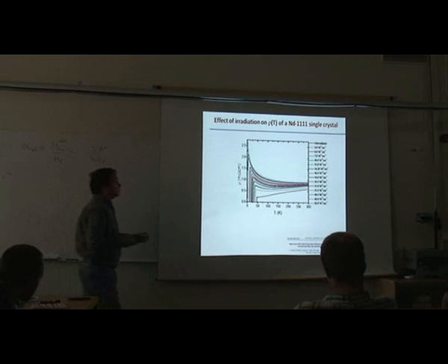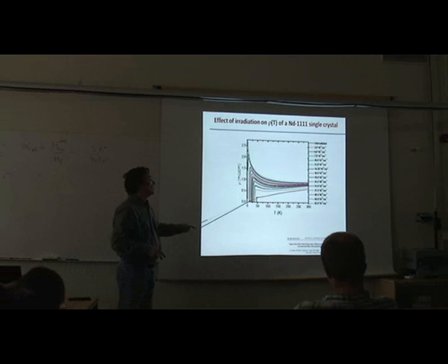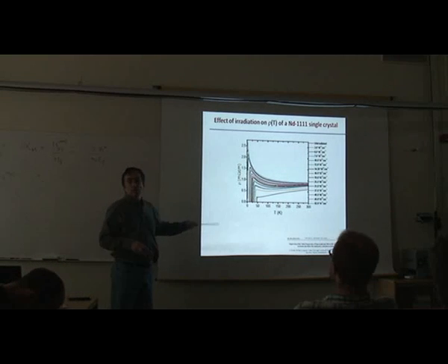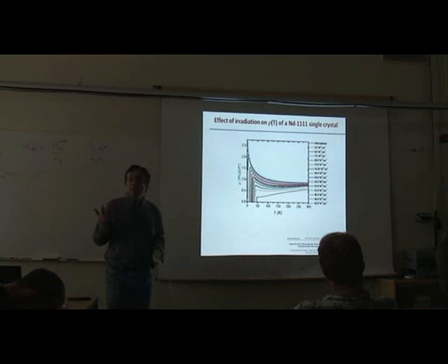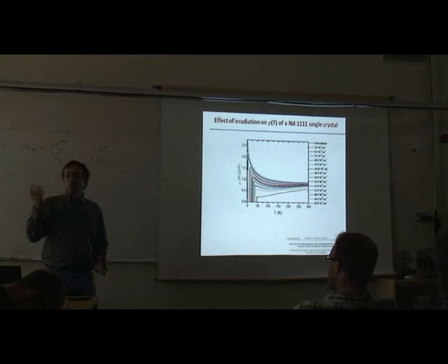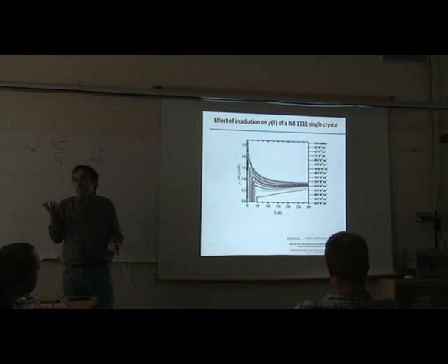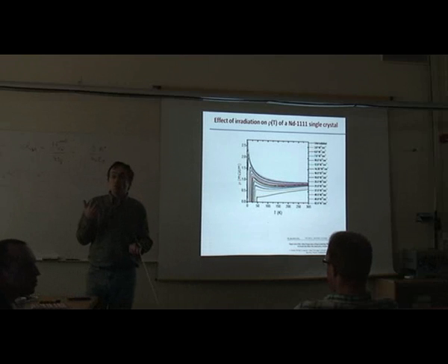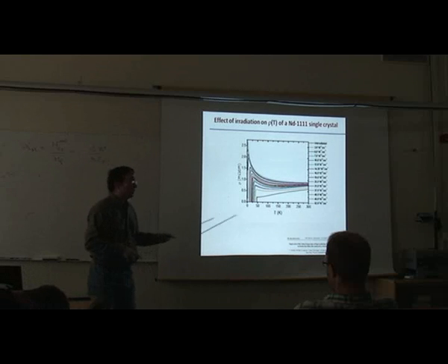But already this picture shows something very unusual. What it shows is this. If you compare resistivity from here, here, and here, the resistivity increased by a factor of 3, 4, 5. That means that the mean free path is 3, 4, 5 times smaller than here. But the mean free path is already short. So all models tell us that when the mean free path in the S plus minus model becomes of the order of xi, TC should go to 0. And it really doesn't.